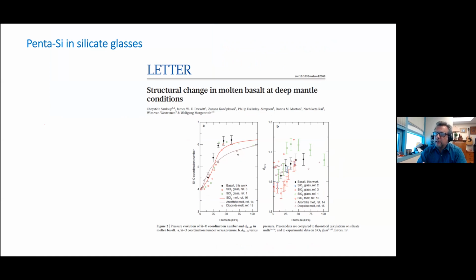So we know for both minerals and glasses, as well as melts, that there are changes in the preferred or dominating coordination number of silicon that happen as a function of pressure and temperature. This is a figure from a paper by Sanloup and co-authors, where a compilation of data was presented showing the changes in the silicon-oxygen coordination as a function of pressure for a number of amorphous phases, including silica, glass, basalts, and so on, and melts. So you can see that we are starting at low pressure from 4. 5 is kind of an intermediate region. There's no particular step at 5. And then 6, which is the octahedral coordination for high pressure phases, is a plateau that we reach at pressure of about 25 GPa or so.